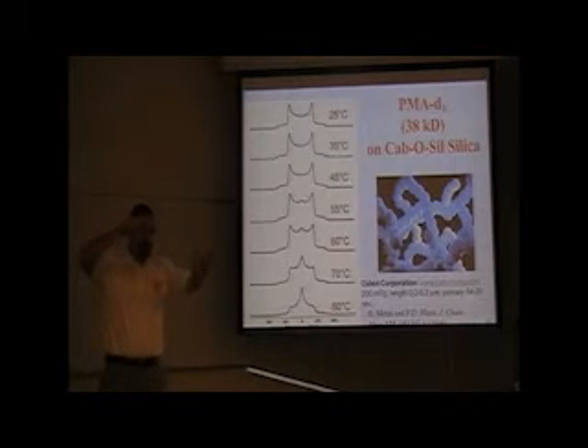And so on the surface, this material is inherently heterogeneous. I said the bulk polymer was homogeneous. This is heterogeneous on the surface. And that makes sense because remember my picture? You had some segments that looked like they were stuck on the surface and you had other segments that were further away. These are the guys that are further away flapping in the breeze. And these are the ones that are at the interface with the silica that are stuck because of that hydrogen bonding. By the way, if they don't like each other, these bets are off. But these guys like each other. They like the hydrogen bond across that interface.